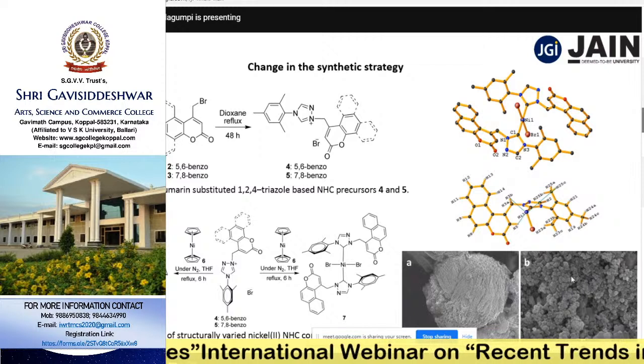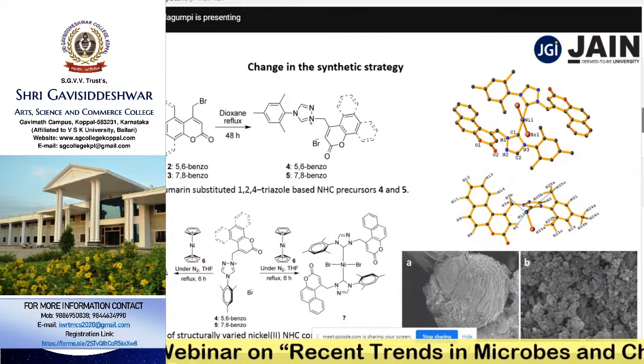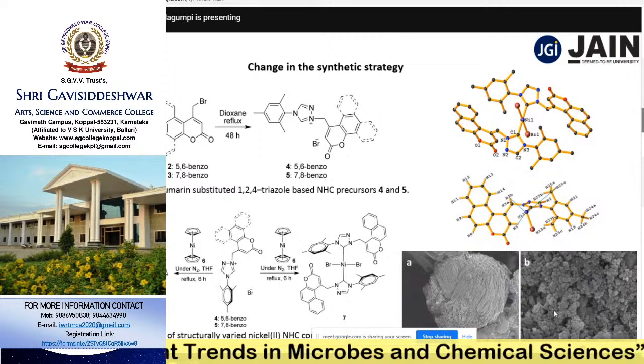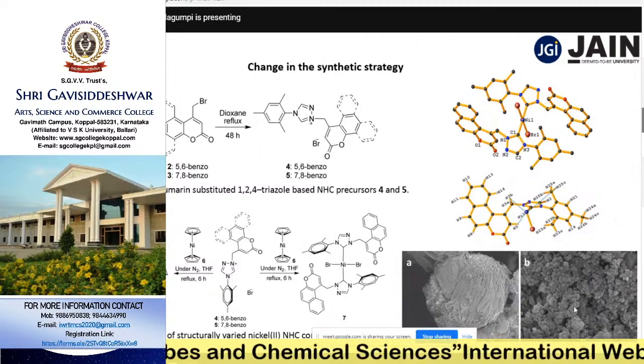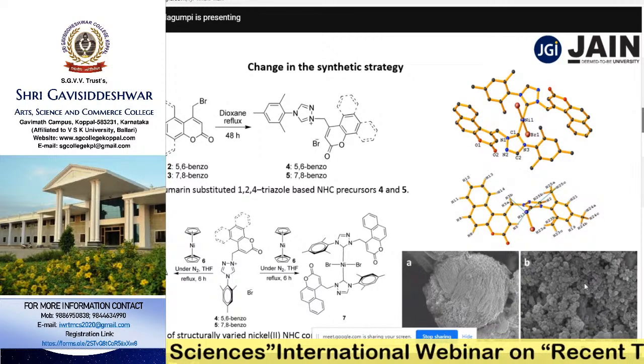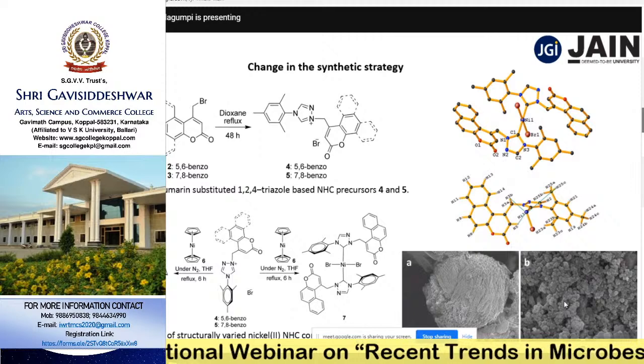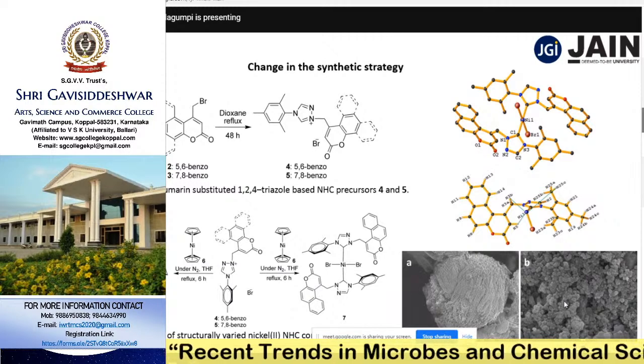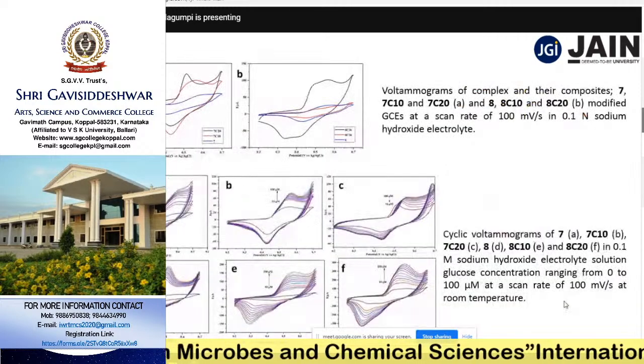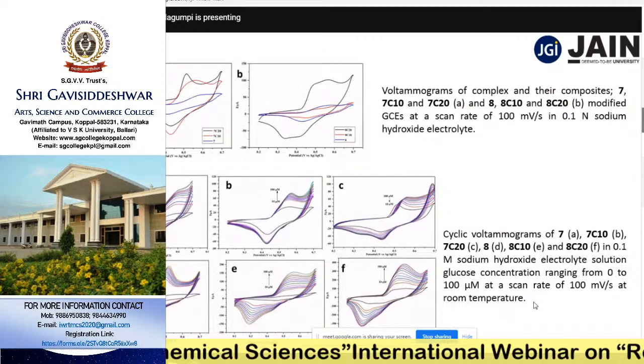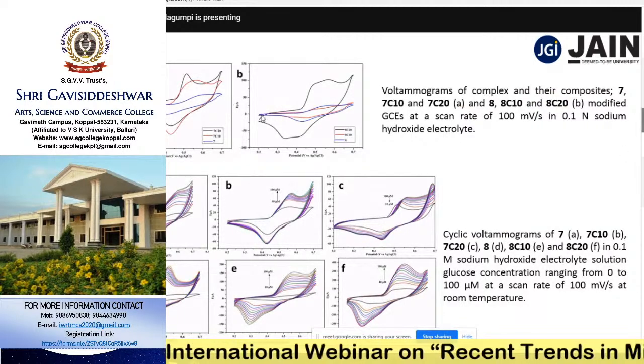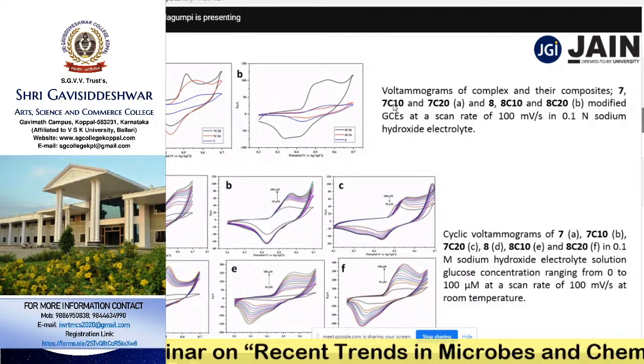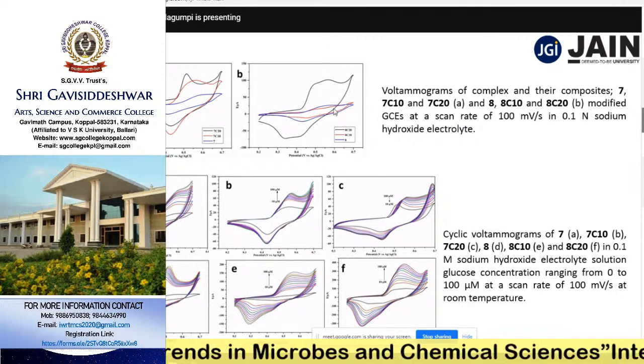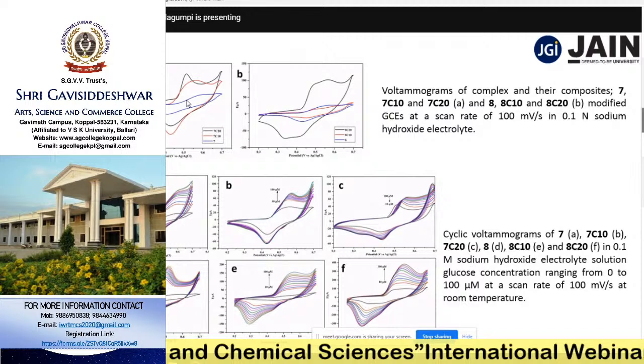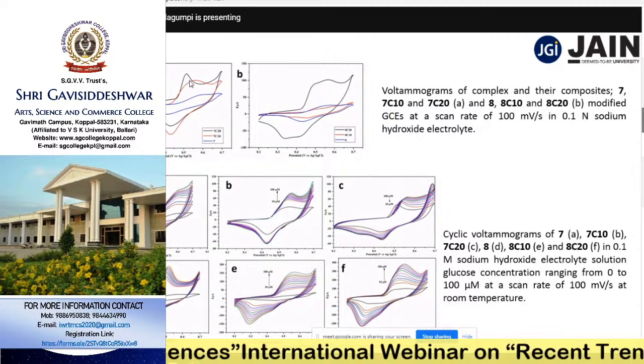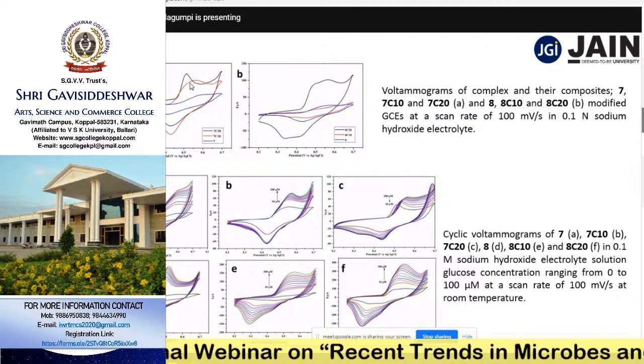So this is almost in the nanoscale. This particular complex appeared in almost nanoscale, and this is a globular structure. This is a granular structure. We call it a nanogranular structure. So we got these things from FESEM analysis. Further again, these complexes were evaluated for the glucose sensing application. Herein, these two complexes were blended with 10% of mesoporous carbon and 20% of mesoporous carbon. So the interior one is just a nickel complex, while these two are the composites of nickel and carbon material.